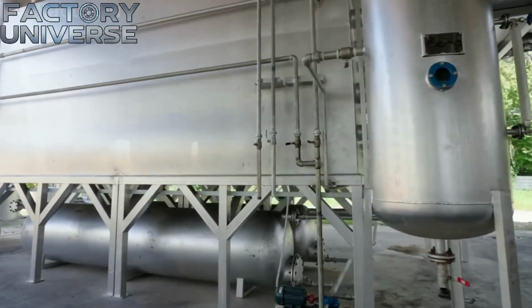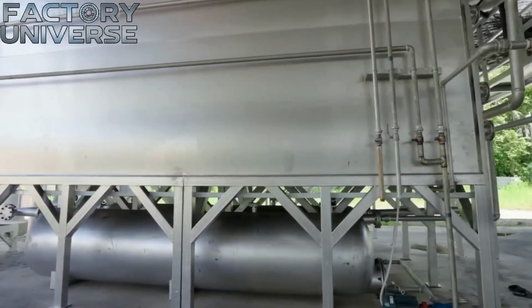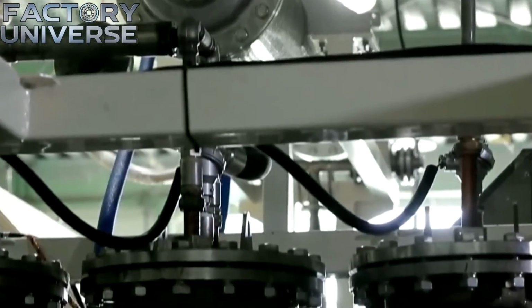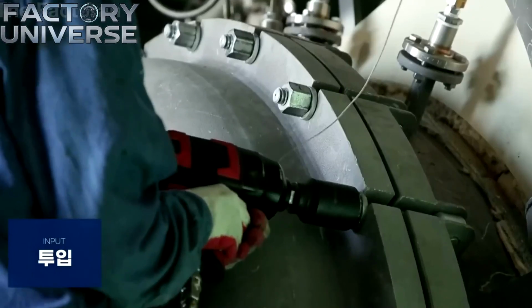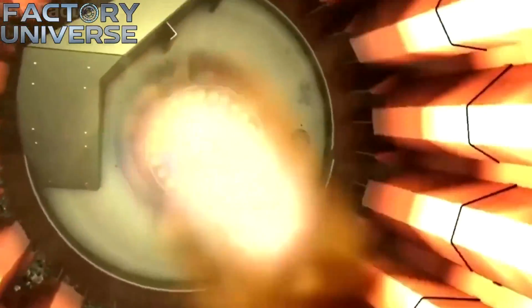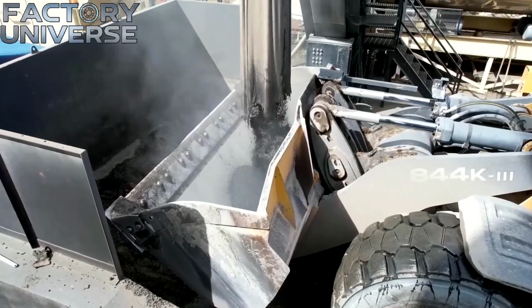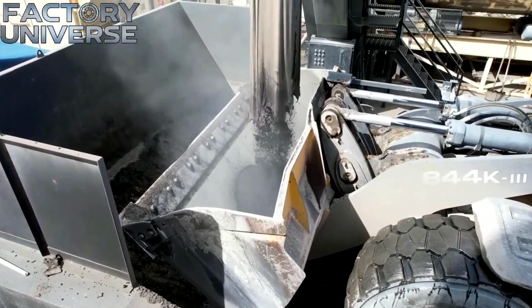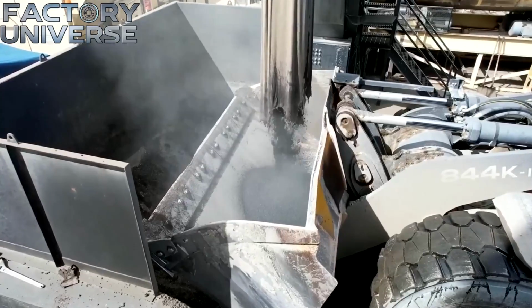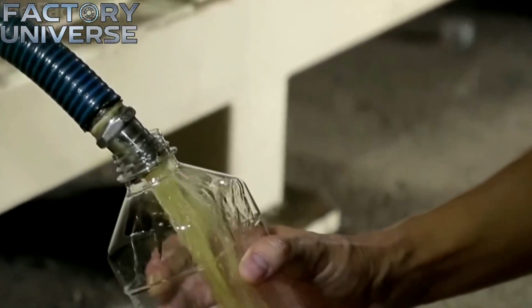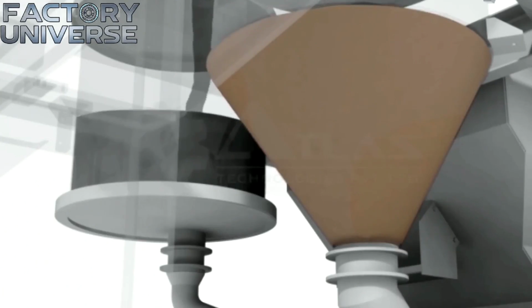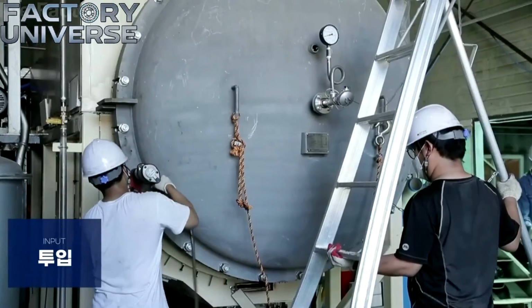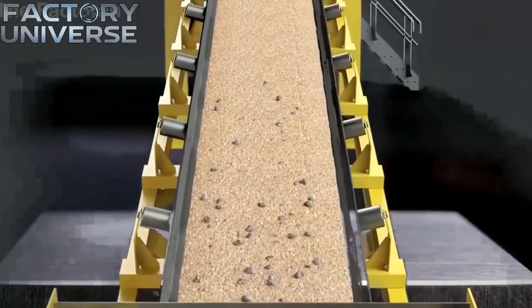The hydrocarbon vapor generated inside the reactor is immediately extracted and sent into the cooling system. Heavier compounds condense first as the vapor moves through the pipes, changing from a gaseous state into a thick liquid and forming paraffin oil. This is the primary product and the most economically valuable output of the entire transformation. After the oil has been almost completely separated, the remaining lighter vapor continues deeper into the system and becomes pyrolysis gas. It does not end at this stage.